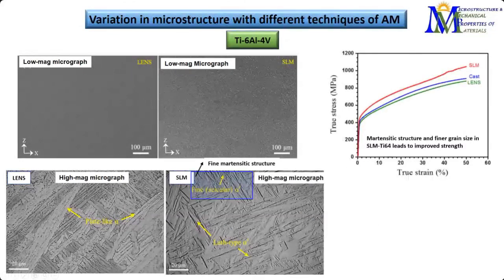Obviously that will lead to variation in properties. So this is the stress-strain diagram, and we see that while the cast one - the conventionally processed one - and the LENS one are more or less comparable, the SLM one, because it produces this martensitic structure, gives us higher strength, higher UTS to failure. So SLM could be preferred in that sense.